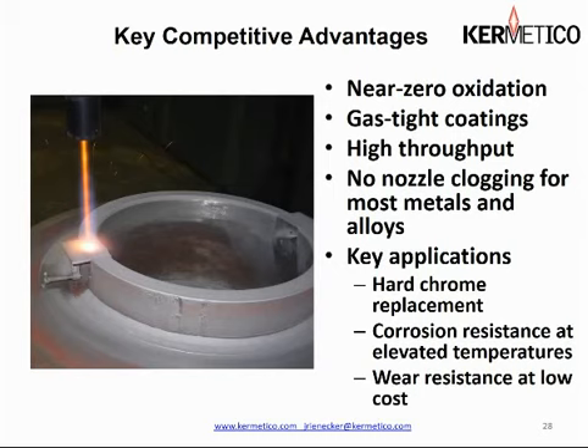So comparing that to an HVOF carbide, or a plasma where you're putting down 1/4 to 1/2 mil per pass, we're putting down 4 to 5 times as much material in each pass. So any job is going to take fewer passes. You're putting less heat into the part, you're watching it cool off for less time. It's much more efficient. And we're not even integrating blasting with HVAF, which is a whole other discussion that saves a ton of time and money in preparing the part for the coating.